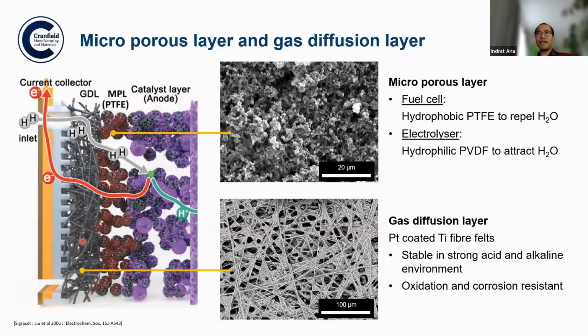These are basically titanium fiber felt. You can look at the microscope image at the bottom center. And these fiber felts are coated with platinum. This is the reason why it's so expensive. Every single fiber of this has to be coated with platinum. First of all, titanium is expensive. It's abundant, but it's expensive because it's so difficult to manufacture. And second, platinum is very expensive.